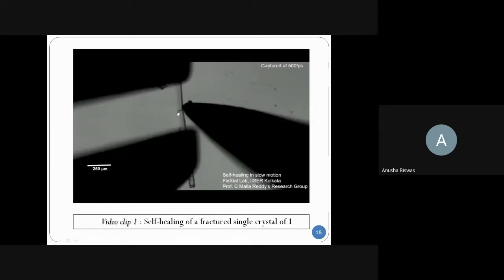Here the crack is introduced by using a 3-point bending test, and after the crack is introduced, as the pieces are physically apart, the surface charge is generated and they are rejoined again. This is another repetition of the self-healing cycle for this crystal. The crack is introduced and it's healing again, and this is repeated in several cycles.